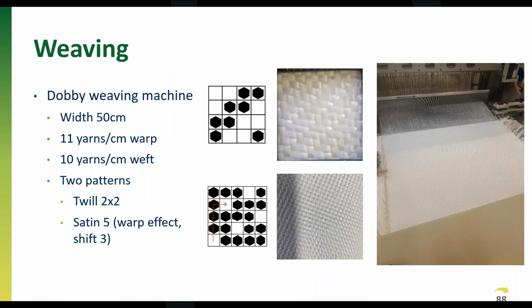So the Satin 5 is just because there you have your yarn passing over 4 weft insertions before going under one, so having it more aligned in the fabric itself. The Twill 2x2 will have a little bit more curves and bends, so also to see the effect of this within the composite formation and the resulting mechanical properties.